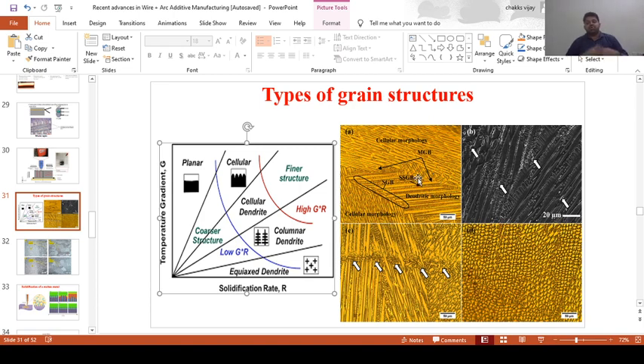For example, if the cooling rate is very high, then we will get an equiaxed structure. This is how an equiaxed structure typically looks. If my cooling rate is very sluggish, then it would end up with a planar structure. If it is intermediate, then we will get a cellular dendrite or a columnar dendrite. Columnar dendrite is the most common structure which we can observe with aluminum, stainless steel, and inconel. Mostly columnar dendrites will form, and an equiaxed structure could also be possible. I will show you exactly how an equiaxed structure looks.